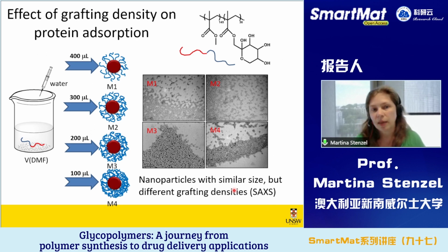So we did the same thing here. We wanted to learn first how the nanoparticle properties influence the biological distribution. What we made here were four different micelles, and they all look the same on the TEM. They all have a size between 20 and 30 nanometers, but they were processed slightly differently. Particle M1, for example, had a very low grafting density, while for particle M4 the aggregation number was much higher, and therefore we had more polymers on the surface. We identified that using small angle X-ray scattering.